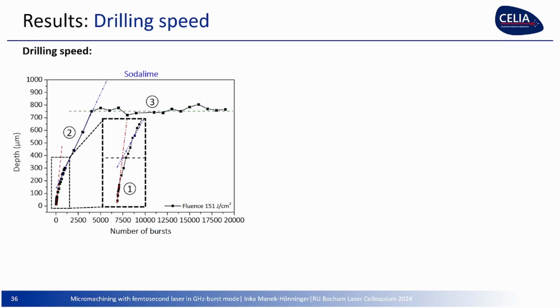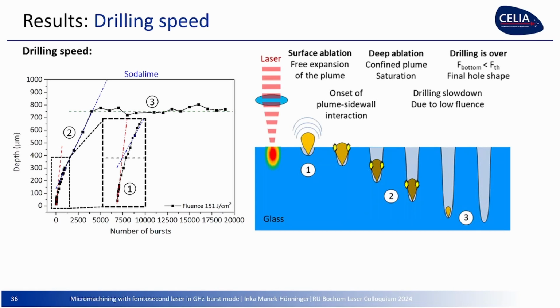What about drilling speed? You can get the drilling speed when you look at the slope of how the curve is rising. And when you have a closer look at the beginning, you see there are 3 curves that you can fit. There's one very steep in the beginning, a middle one, and then the last one, which corresponds to the saturation. So this gives us a mechanism of drilling in 3 stages. First, we have the surface ablation where the plume can freely expand. Then it starts to interact with the side walls. And here you have some other effect, that's why the slope changes. Here drilling is a bit slower. Here it is faster. And then finally, there's no more energy left.